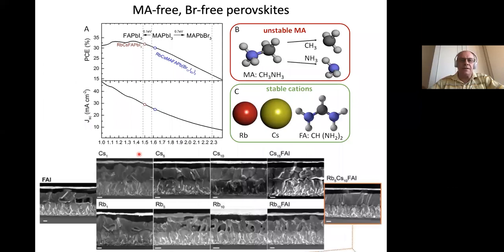And what is interesting for us is, if I take this a bit quickly, here are cross-section SEM pictures. If you take FA only, without cesium and without rubidium, you have voids, a bad morphology, let's say. We start to add cesium, 1%, 5%, 10%. Morphology is much better, and the solar cell also works quite well, 17-18% with 10-15% cesium. If we take the rubidium instead, it's always poor morphology. Big voids, very poor solar cell efficiency. Interestingly, it is the combination of 5% rubidium with 10% cesium and the rest FA, which gave us the best results and best morphology. So this is also an intriguing thing with the compositional engineering, how to tune your composition to find the best results.